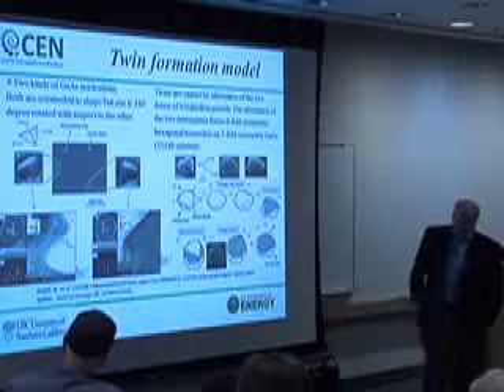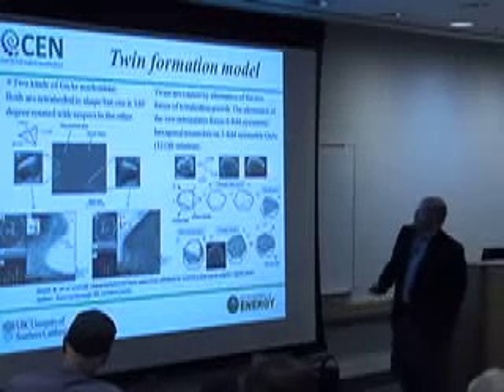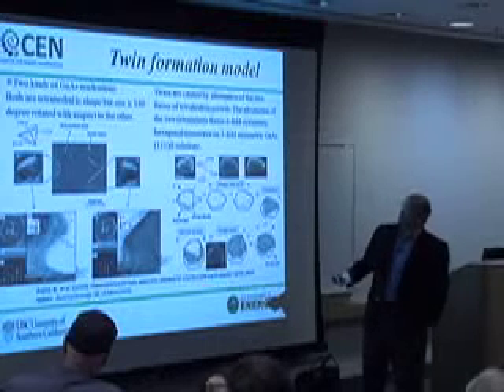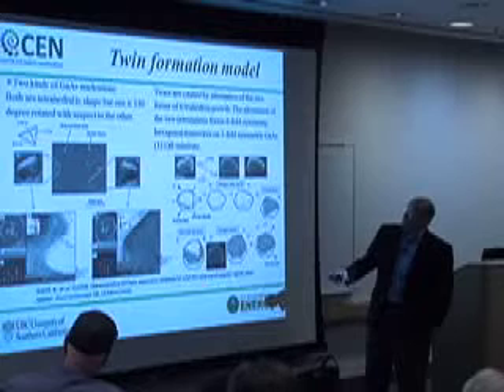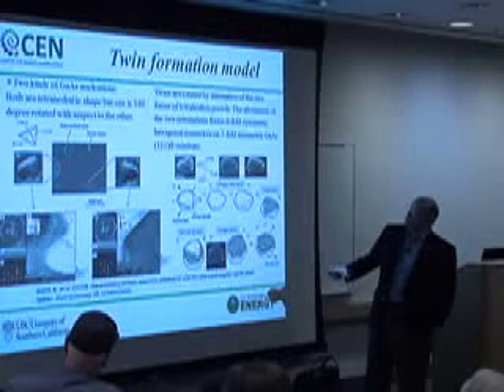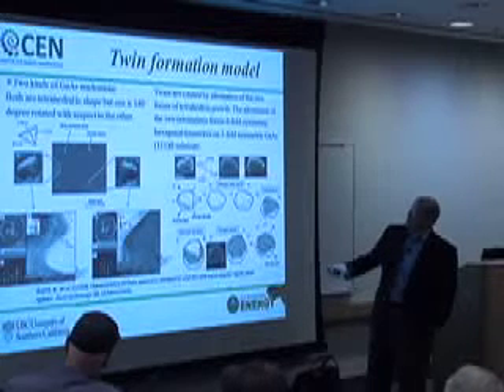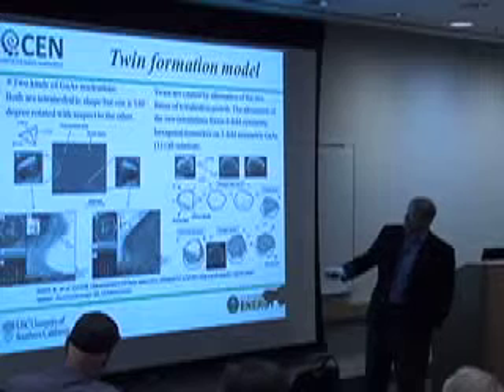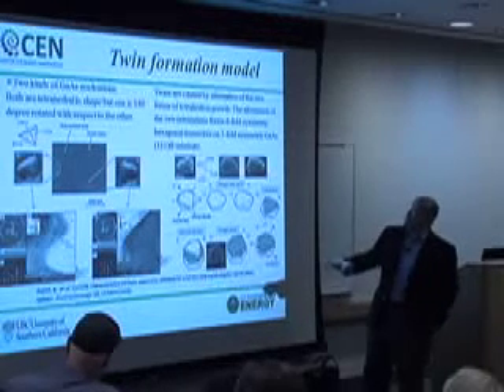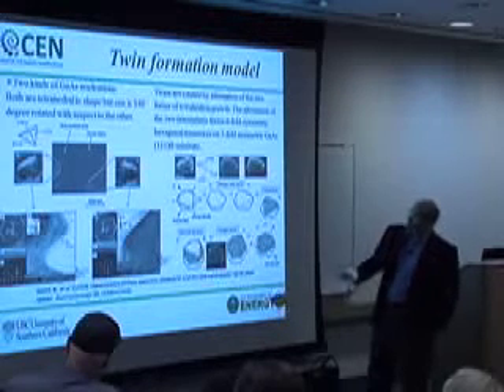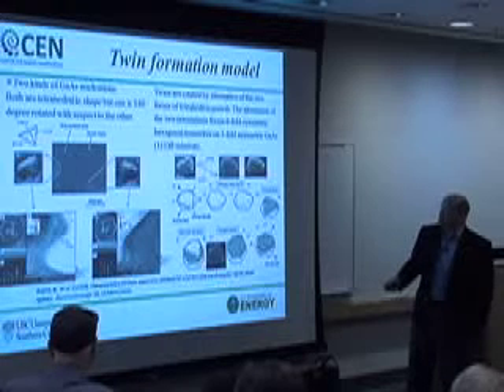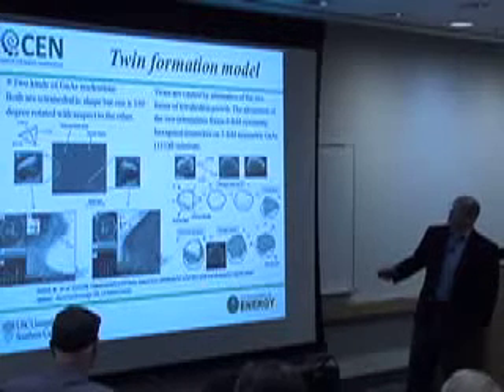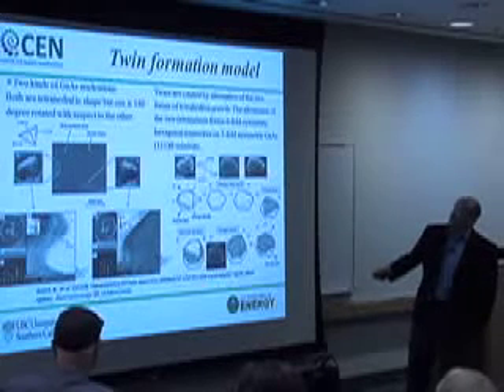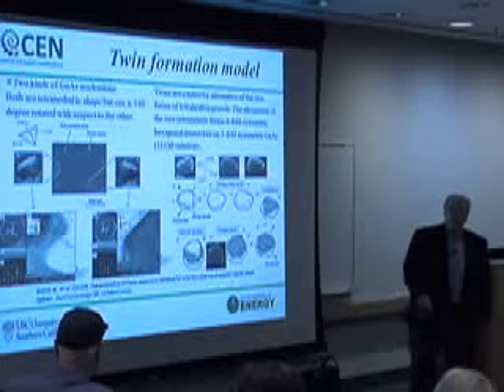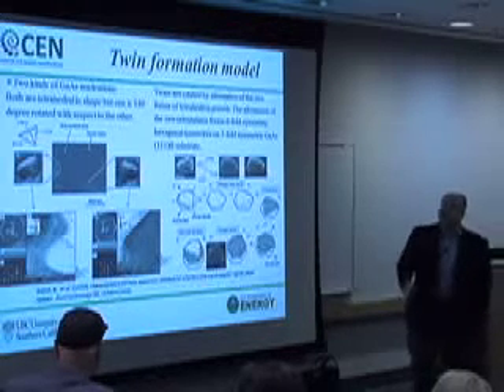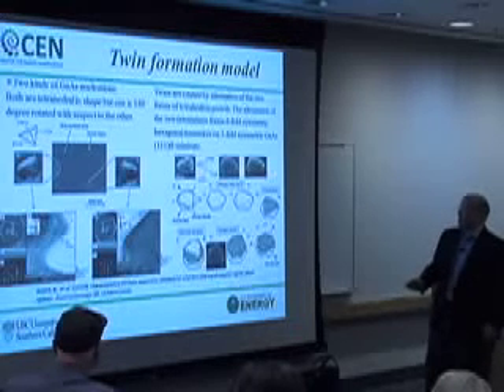But there's also been some work done in Japan at Fukui's lab where he's looked at the initial nucleation of gallium arsenide in small openings, and he's seen that the initial nucleation takes one of two forms. They're tetrahedra, and they're either aligned along the 1, 1, minus 2 direction or the minus 1, 1, 2 direction, which are 180-degree rotations of that tetrahedron with respect to one another. Upon closer study, he found that this is the preferred orientation for the growth of the zincblende crystal. This orientation quickly forms a twin boundary in the layer, so that the crystalline structure rotates by 180 degrees.